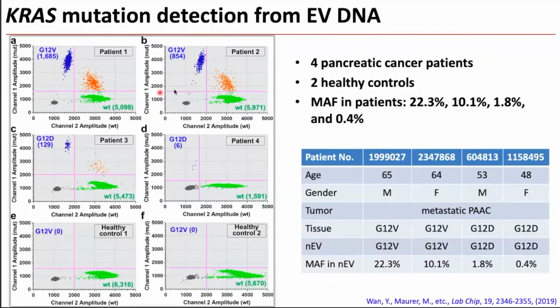So in this study, we did a little bit of a pilot study. In this case, the top 4 are samples from patients, and the bottom 2 are from healthy donors. As you can see, these are 4 patients with pancreatic cancer, and these blue dots are the droplets with the mutant copy, and the green dots are wild type copy. The orange ones we think actually contain both the mutant copy and the wild type copy. What we see here is a wide range of mutant allele fraction within these samples. In these 4 cases, it's from about 22% down to 0.4%. So that again highlights the importance of detection sensitivity after the EV enrichment.